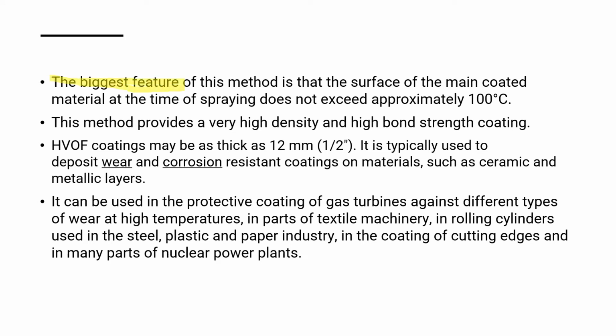Okay, the biggest feature of this method is that the surface temperature of the main coated material at the time of spraying does not exceed approximately 100 degrees. This method provides very high density and high bond strength coating. High velocity oxygen fuel coatings may be as thick as 12 mm. It is typically used to deposit wear and corrosion resistant coatings on materials such as ceramics and metallic layers. It can be used in the protective coating of gas turbines against different types of wear and high temperatures, in parts of textile machinery, in rolling cylinders used in the steel, plastic, and paper industry, in the coating of cutting edges, and in many parts of nuclear power plants.